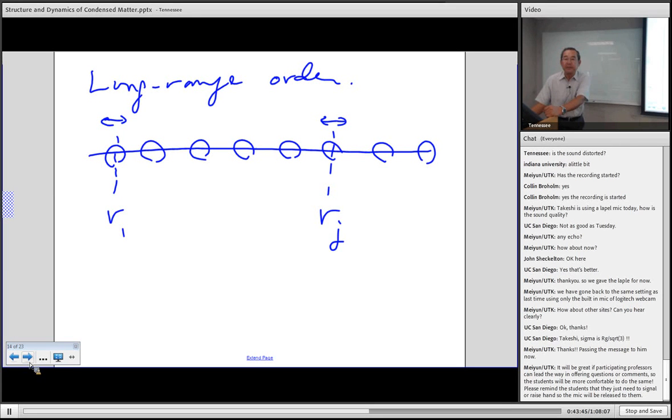So if you do a measurement which corresponds to a long time average, that is static diffraction, omega equals 0, that elastic measurement does not exchange momentum with each atom. Elastic measurement exchanges momentum with the whole sample. So in this case, the order or atomic position of the time-averaged whole sample remains the same.